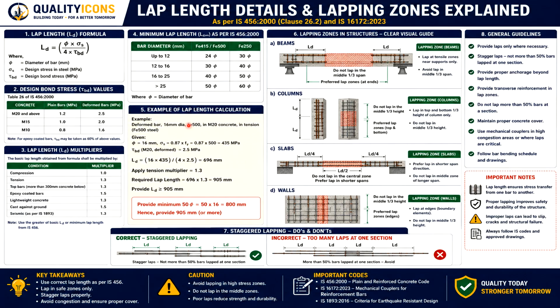Example of lap length calculation. For example, 16 mm diameter bar, grade Fe 500, M20 concrete, in tension zone. For Fe 500 steel, 16 mm diameter, design stress is 0.87 into fy, where fy is the grade of the steel, so 435 megapascals. Design bond stress τbd for M20 deformed bars as per IS 456 is 2.5 megapascals. LD = 16 × 435 / (4 × 2.5), that is 696 mm.